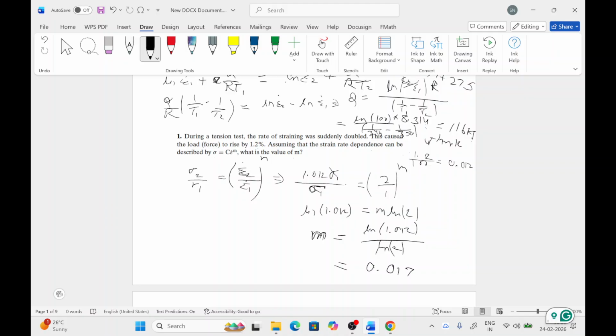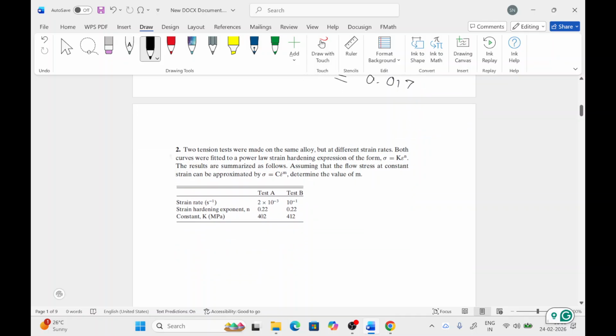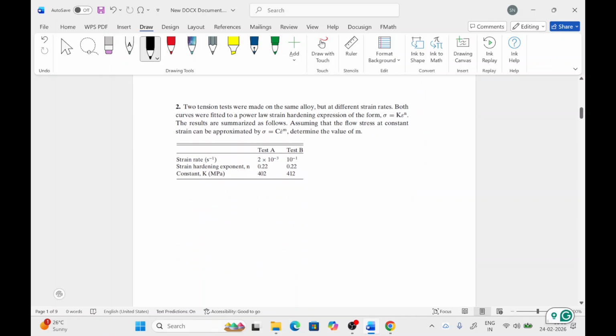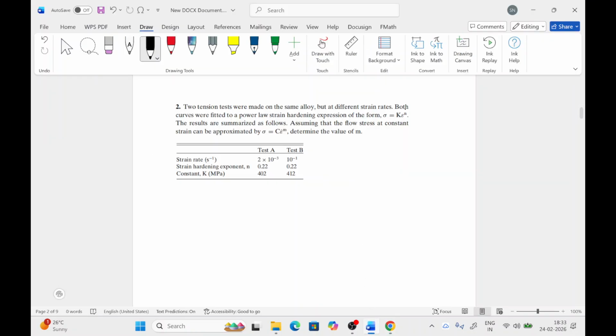Okay, so the next question is based on the same. Two tension tests were made on the same alloy, but at different strain rates. Both curves were fitted to a power law strain hardening expression of the form sigma equals k epsilon raised to power n. So this is the power law for the strain hardening.